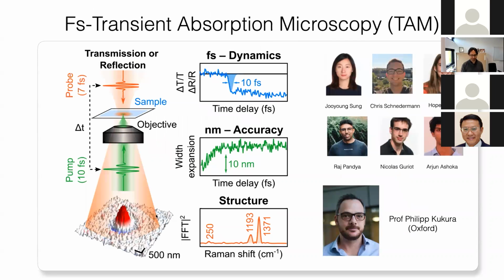And essentially, this is what the data looks like. One measures these Gaussian profiles, and one can see expansions. So this is to say the motion of excitons or whatever quasi-particle we have. We can measure this with about 10 nanometer precision very routinely in the best materials. If we try very hard, down to 2 nanometers, and the time resolution is very high.